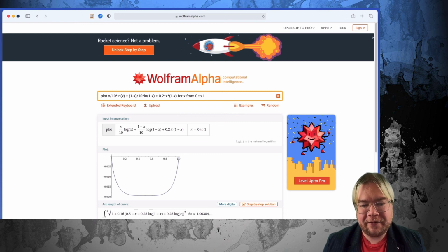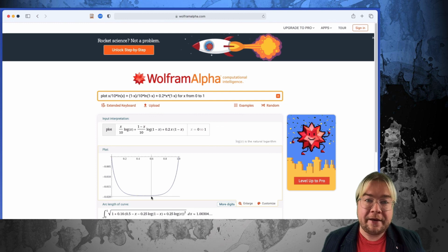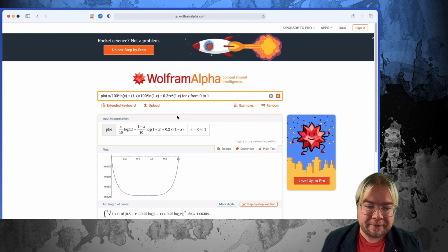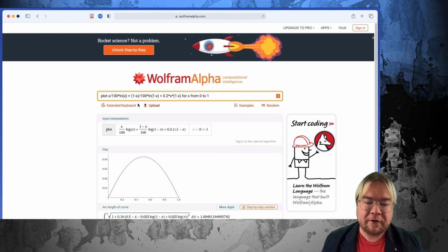So you see that the degree of polymerization, as you make your chains bigger and bigger and bigger, this curve goes from being negative to being positive. So in this instance, the particles will likely mix together. And the ones that I just showed you for the larger molecular weights, where you have degrees of polymerization of 100 or more, you see that the curve is positive for all values.